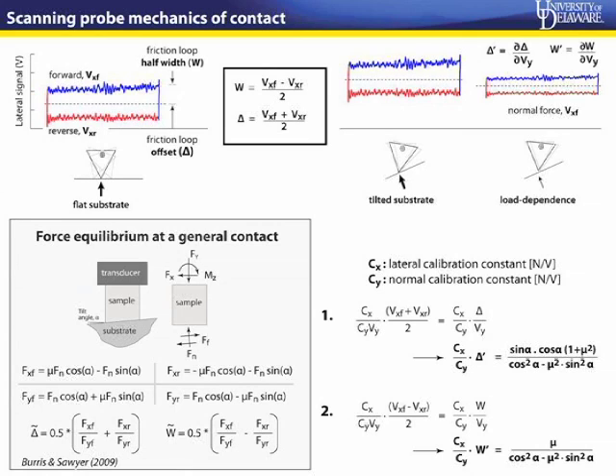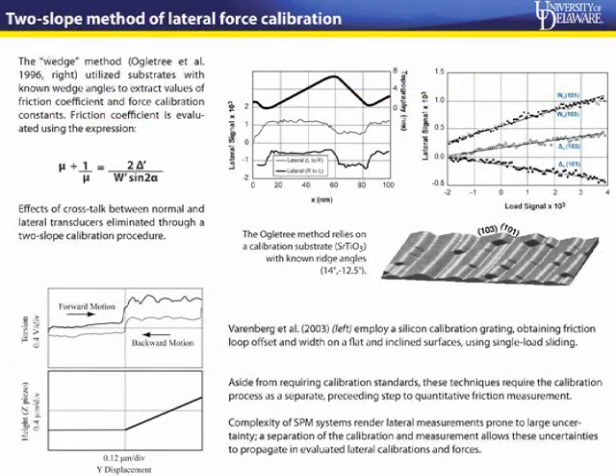Now, using this formulation of a tilted substrate, there have been a few methods that have sought to calibrate AFM cantilevers. One of them, the classical wedge method, which was proposed by Ogletree and others back in 1996, actually uses a given calibration substrate with two known angles. And what they do is slide on these two ridges of the substrate and essentially end up with a friction loop which goes up and down. Again, these are just changes in the offset. And if you do the load dependence, you essentially end up with W primes and delta primes, which are the slopes of these lines. This is essentially what I showed in the previous slide right here.